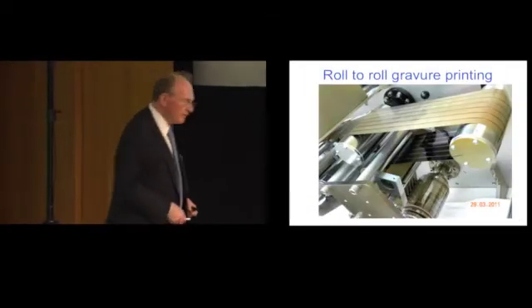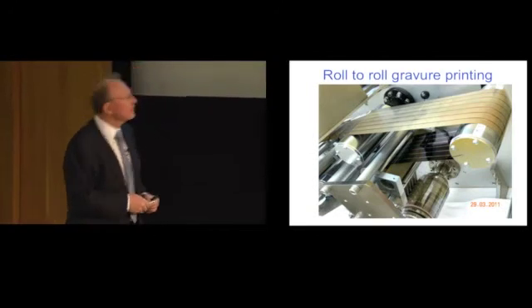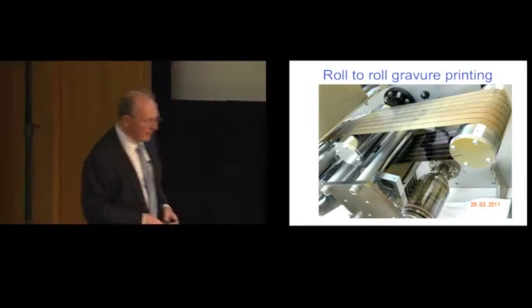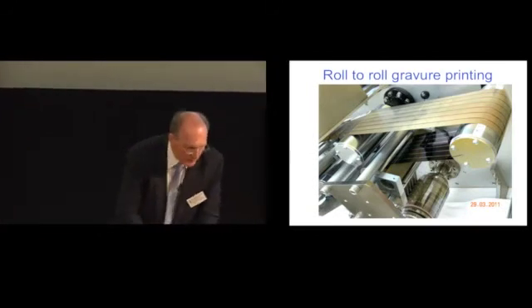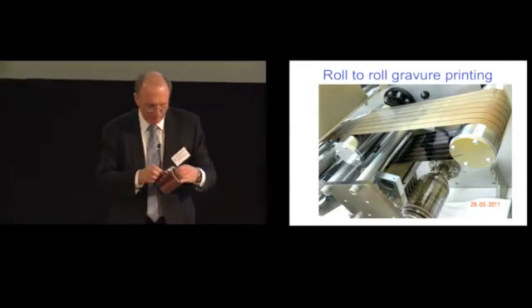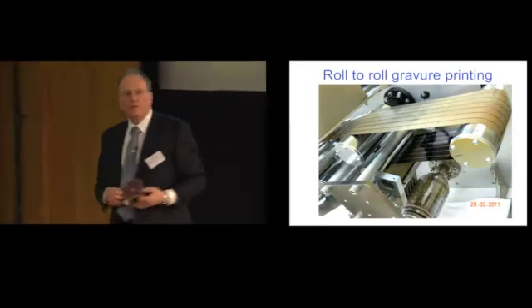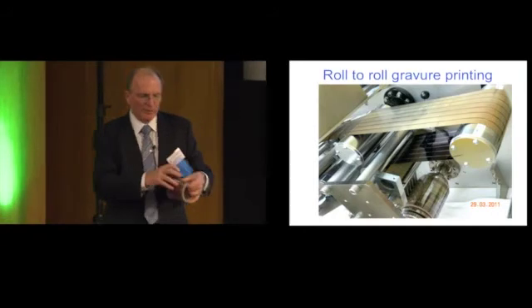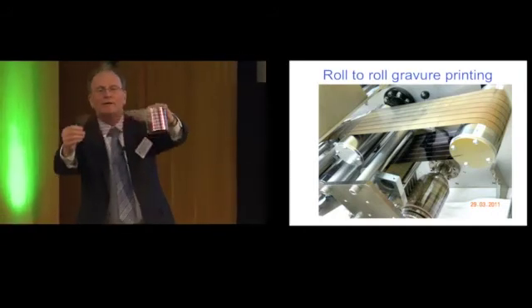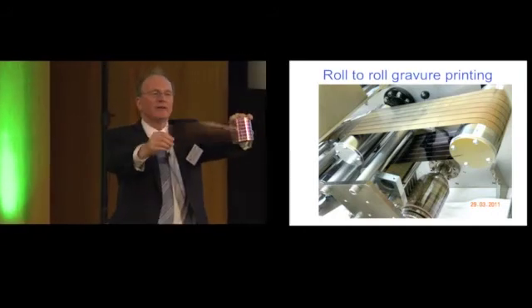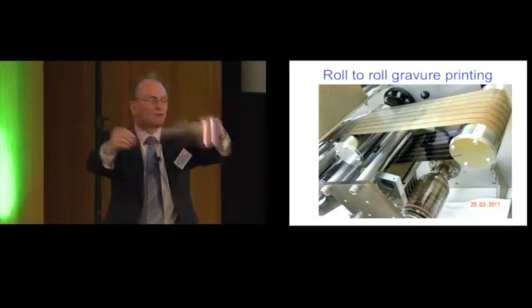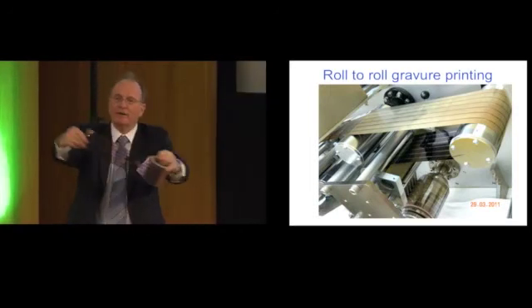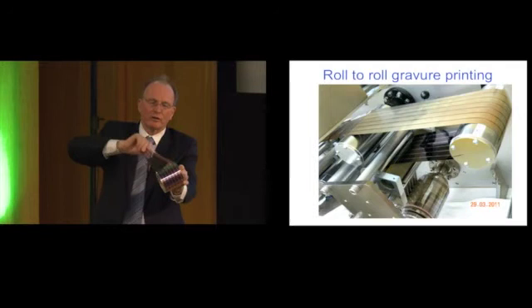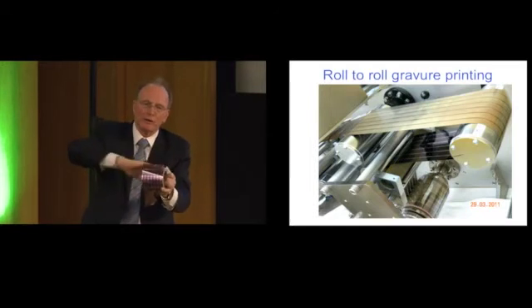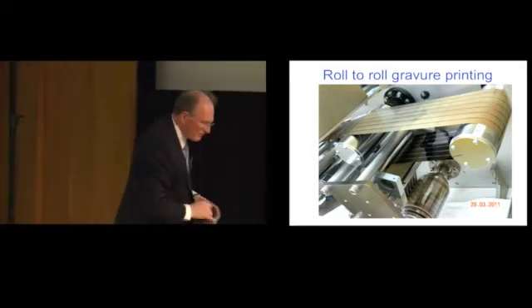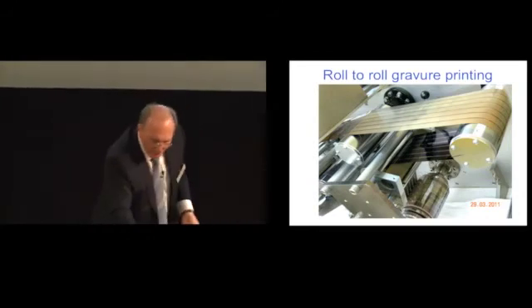And here's our printer. This is called gravure printing. This is a mini labo printer. And I've got a film of the print that's being used here. This is the polyethylene terephthalate with indium tin oxide. And there you see the blend of the red poly-3-hexylthiophene and the fullerene printed on this. This is exactly printed on that printer. And this will be a solar cell when we finish it off with one more electrode on top. So that's how the solar cells are printed.